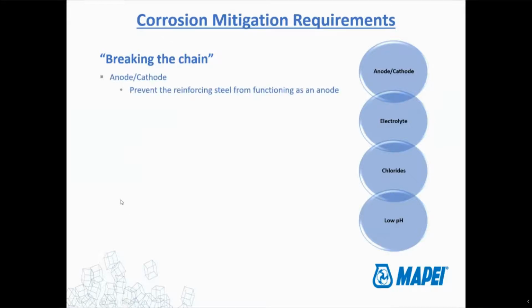So if you remember those equations that I showed you, that I said don't worry about, we don't need to remember them, and you don't. But if you just at least for a moment remember those, if we take any one of those components away, if we take away the anode or the cathode, or we remove the electrolyte, which is basically the water in the concrete, or if we remove the chlorides, or we take a low pH and make it a high pH, if we do any one of those things, we're going to break that chain of corrosion. That whole set of equations, those chemical reactions that I showed you, can't happen unless all of those items are there. So if we remove just one of them, then we can stop the whole process from happening.